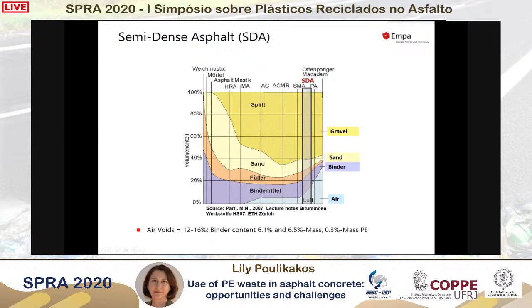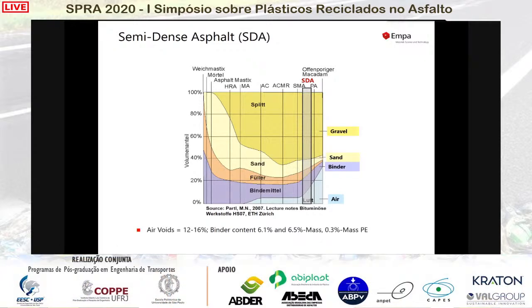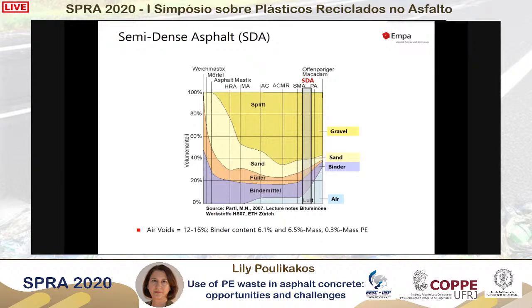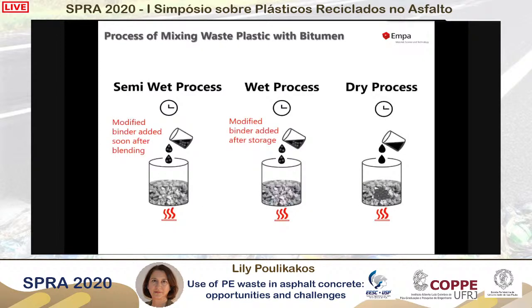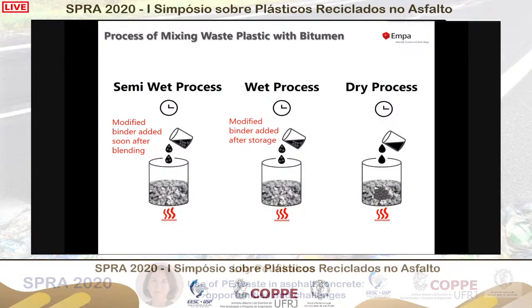So the mixtures that we have used have 16% porosity or air void. They have a binder content of 6.1 or 6.5%. And the ones that are modified with polyethylene have 0.3% by mass of polyethylene. There are various ways of producing the mixtures, and there is the dry process, where the additive or the plastics can be added to the hot aggregates, and then the hot bitumen filler is added to it.